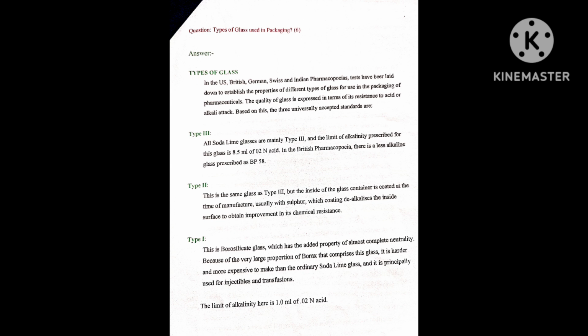This is borosilicate glass, which has the added property of almost complete neutrality because of the very large proportion of borax that comprises the glass. It is harder and more expensive to make than the ordinary soda lime glass, and it is principally used for injectables and transfusions. The limit of alkalinity here is 1.0 ml of 0.02 normal acid.